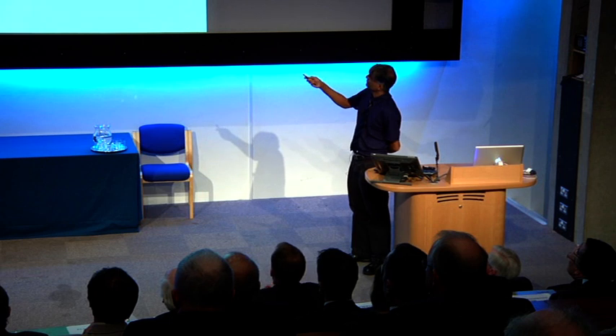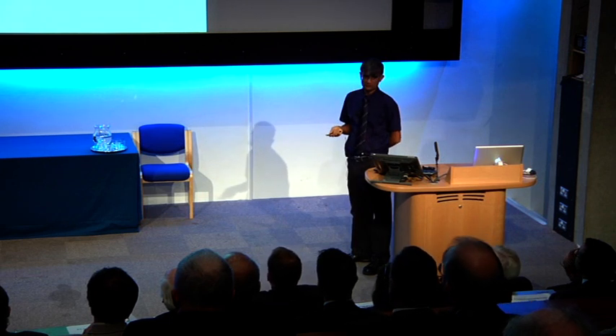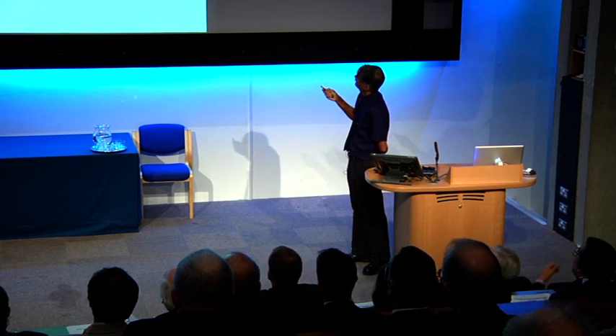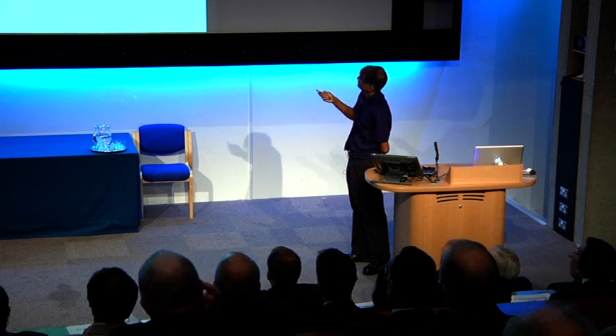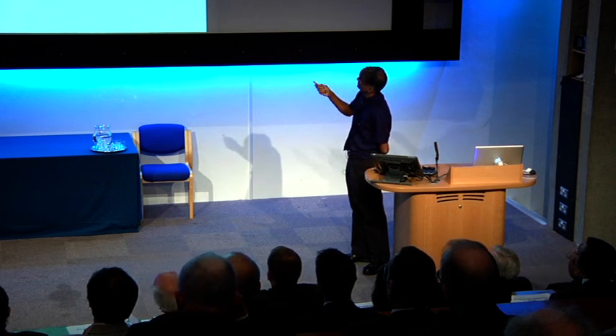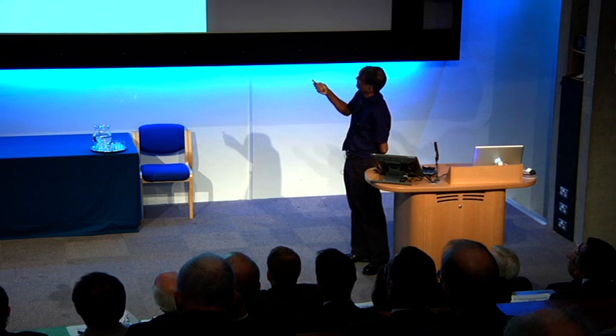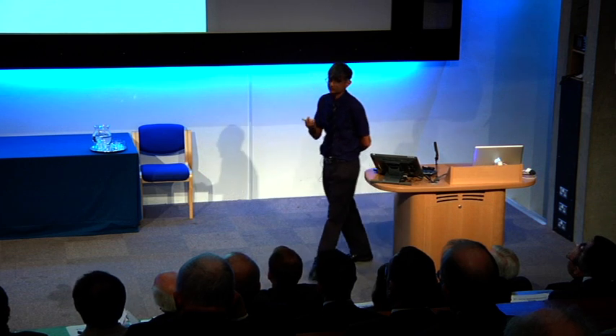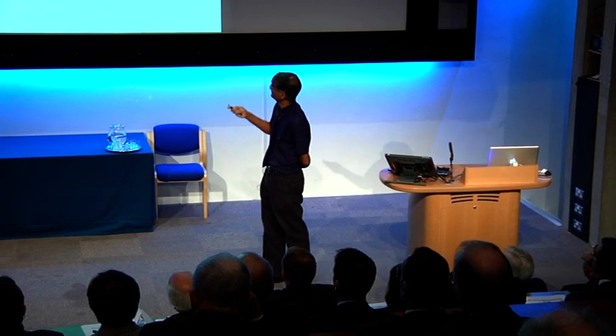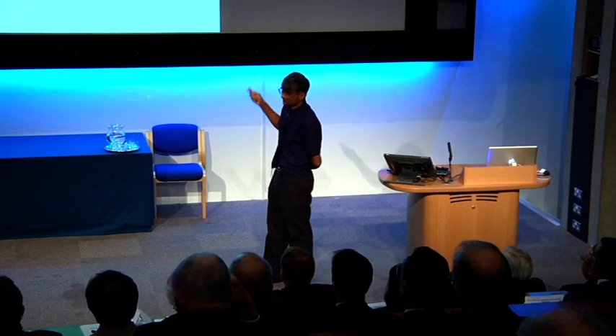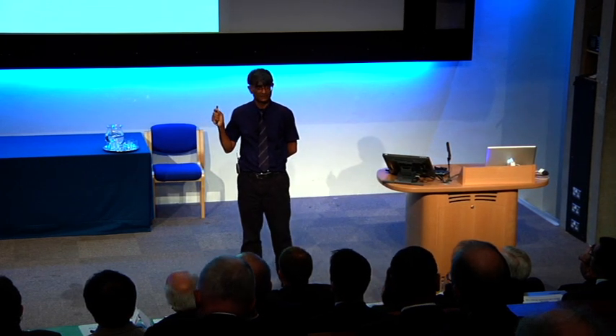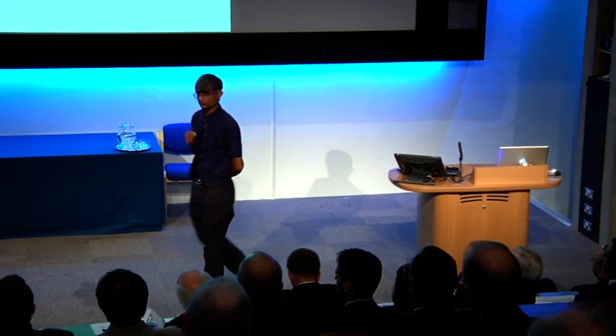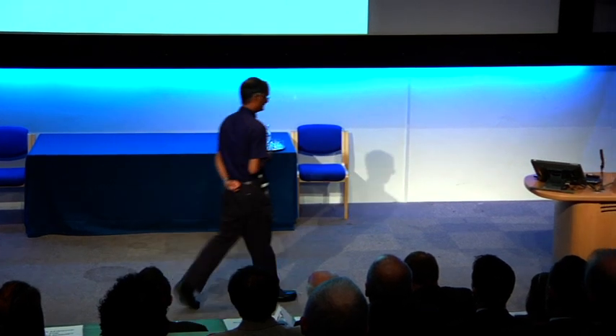And if you look at the previous work, which was published long ago, that would predict the transition from the divorced to the lamellar structure according to this line, and this is the new theory where we have a much bigger domain where we can produce this divorced structure, and indeed the critical experiments here validate that neglecting the role of chromium diffusion is not good enough, okay, because that has a big impact on the kinetics of pearlite.